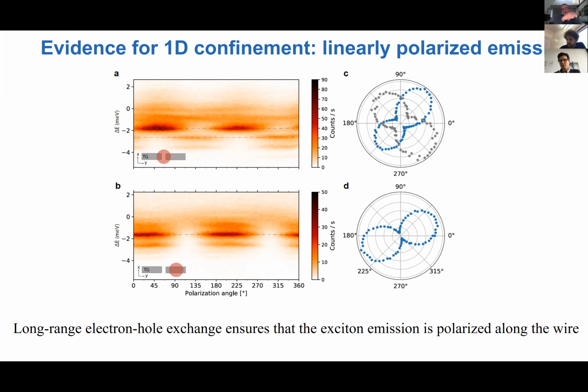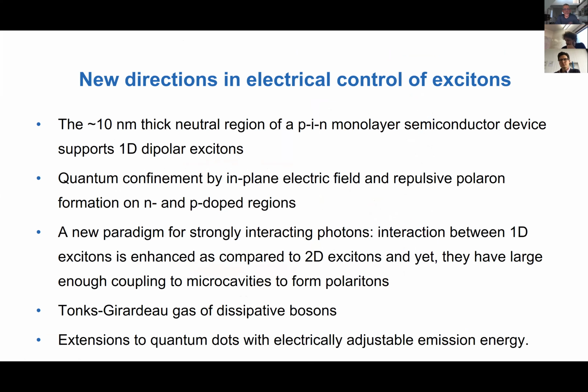And it is well known, for example for carbon nanotubes, that the emission is always polarized along the axis of the 1D wire. If you go to this gap region, we have two kinds of wires, right? One is essentially along this long edge, and one is along the short edge. And then consequently, we see polarization of both types, showing us that even in this 200 nanometer region, we actually have confined excitonic states. Okay, so this I find, as I said, exciting because we can actually create quantized excitonic states.